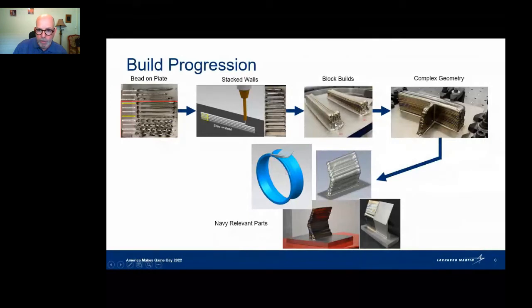We went on to build a more complex geometry. Unfortunately, this is not the best view of this, but essentially, this is a large wall build with another perturbation wall that's a single bead layer going up, and is actually angled down as it goes out. So we progressed to that more complex geometry. In each of these cases, we used specimens from these builds to determine material state, and we did some mechanical properties testing to correlate that material state to the mechanical properties.